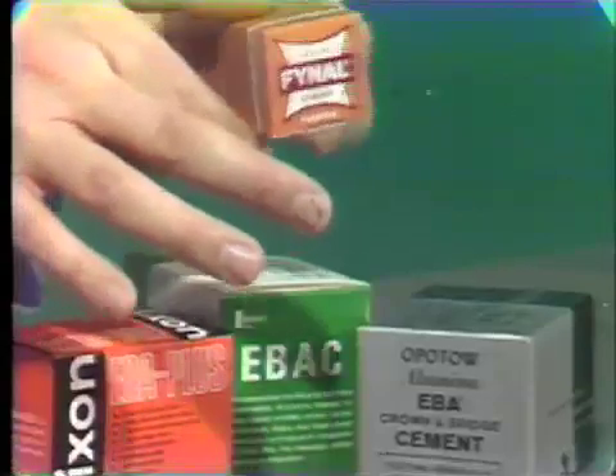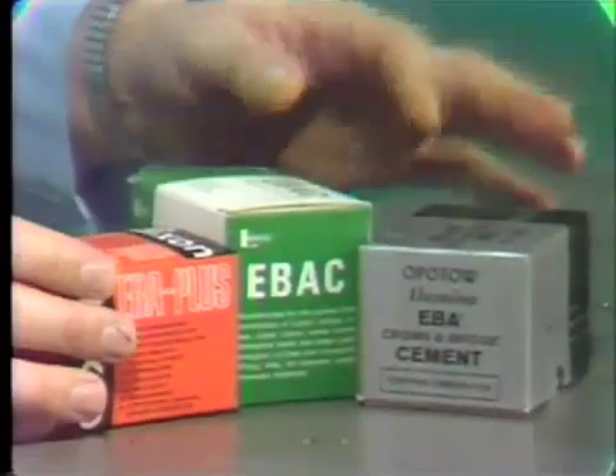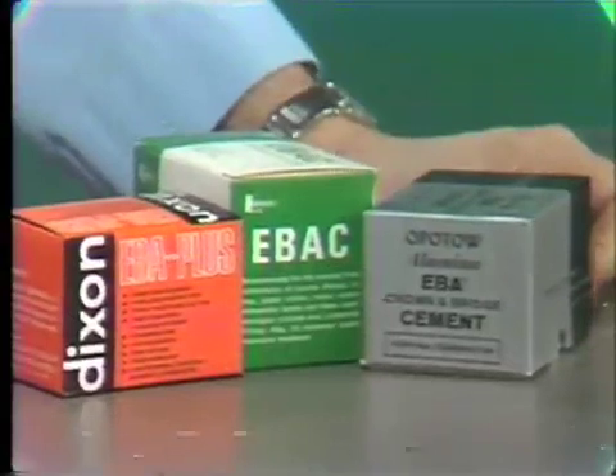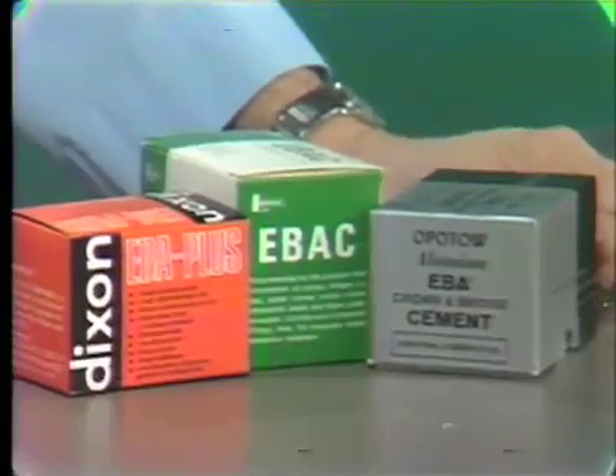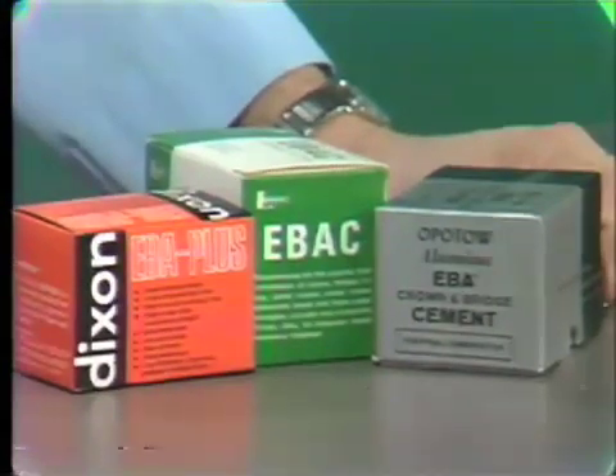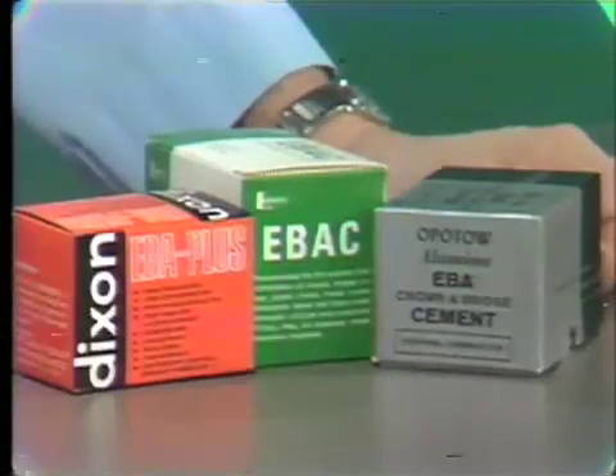The next group of cements I'd like to talk about are the zinc oxide eugenol cements. Most of them are reinforced with alumina and have ethoxy benzoic acid added to them to give them strength. The first one does not have the alumina, and this is Fynal cement. It is a rather weak cement and has a strength of around 7,000. The other zinc oxide eugenol cements with the alumina added have a little more strength, and they are in the range of 10,000 as far as the strength is concerned.